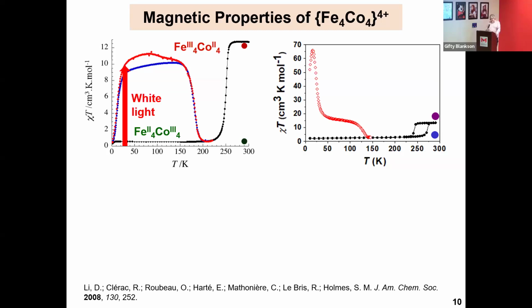But what's interesting, and we counted this for a number of years, is that as you increase the temperature from 1.8 towards 300 Kelvin, the thermally trapped and photo-induced states relax at the same rates. No one had ever seen that before. And that suggests that there's some sort of vibrationally involved state separating the optically and thermally trapped states in its relaxation.